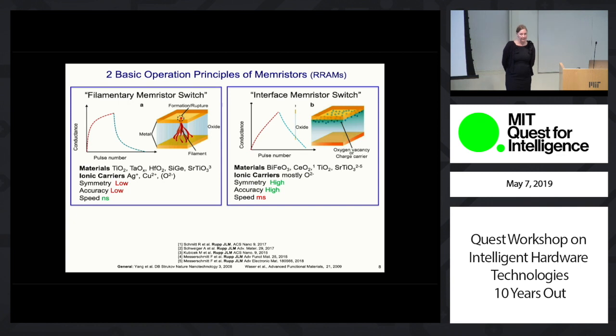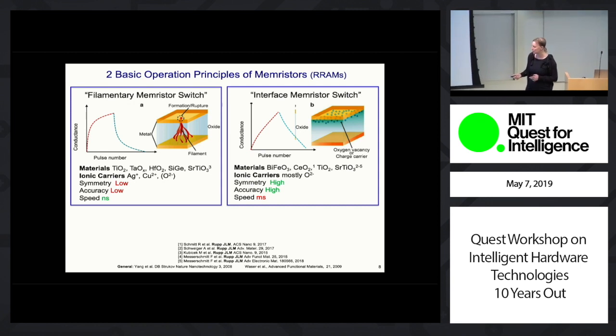And it's not necessarily determined by the processing alone. Even if you have made a strontium titanium oxide memristor, depending on the electric field strength, the pulse frequency or your sweep rate, it can be either bipolar or filamentary switching. So it's one of those exceptional materials that can have both, depending on which range you operate it in. There has been a paper from our group, Kubitschek et al., showing that there can be dual switching, and another group probed it with an AFM tip, Rainer Waser's team in Aachen, if you want to read more about that.